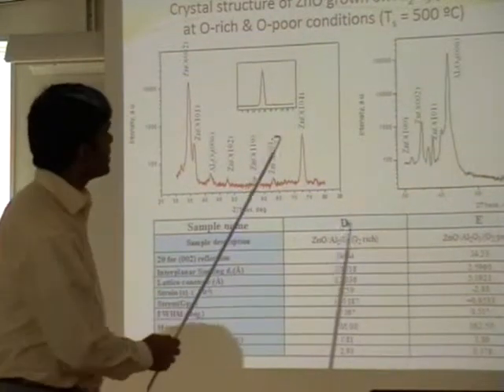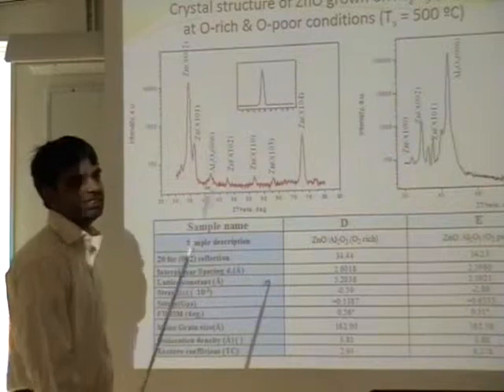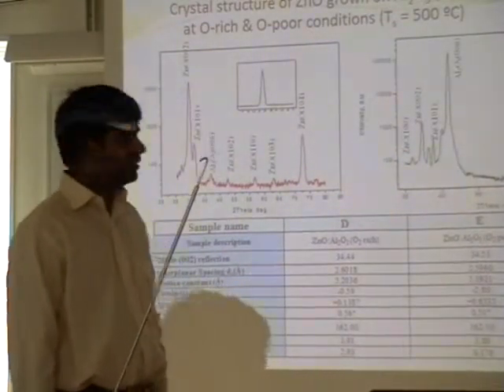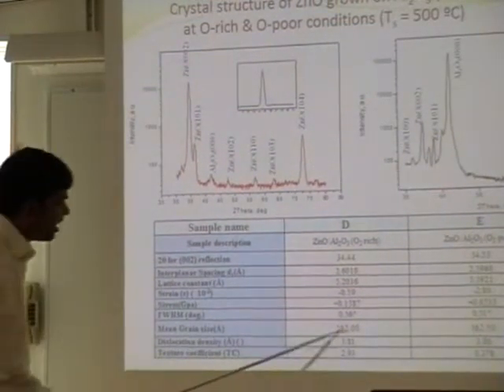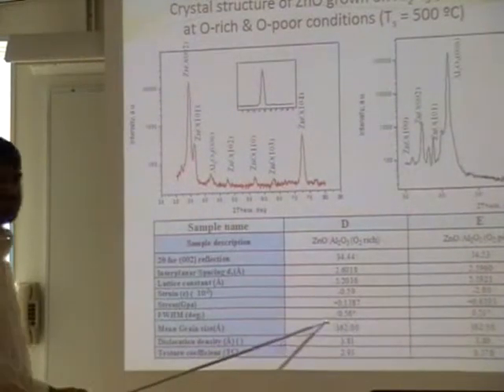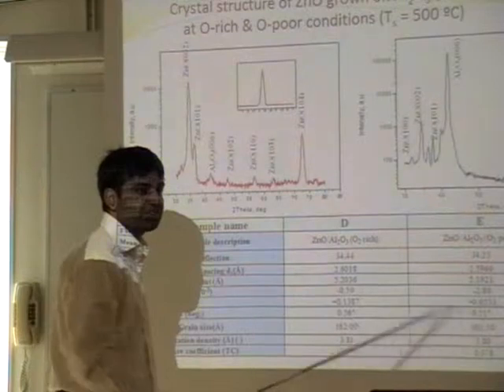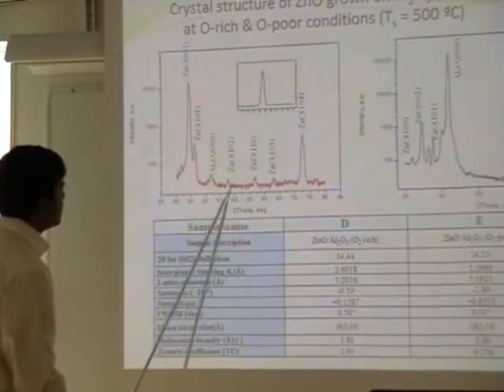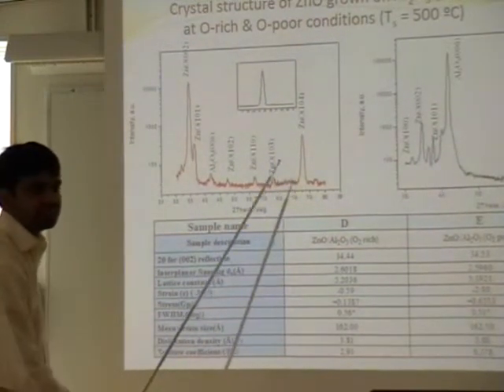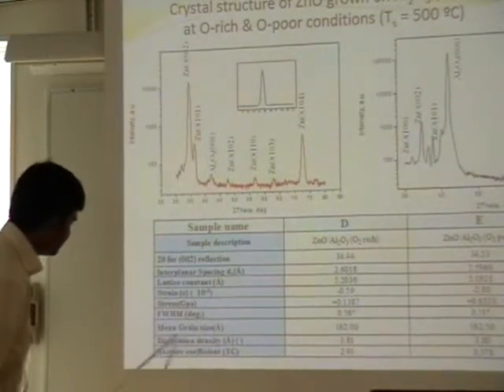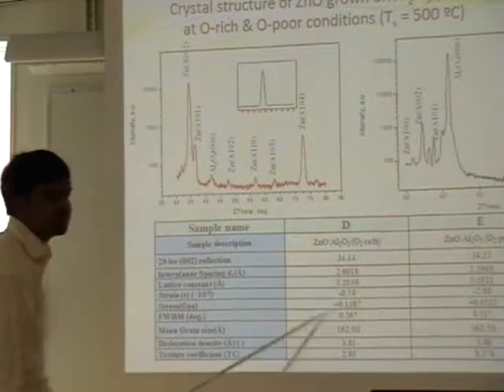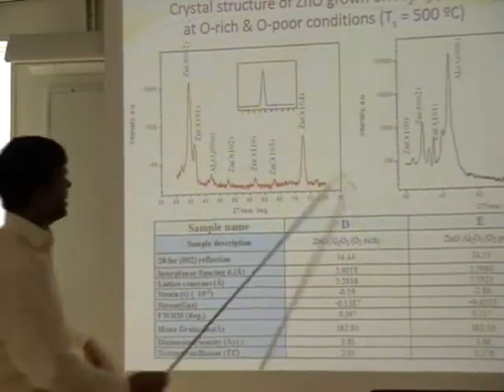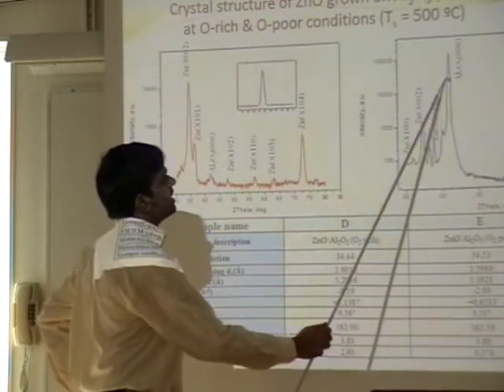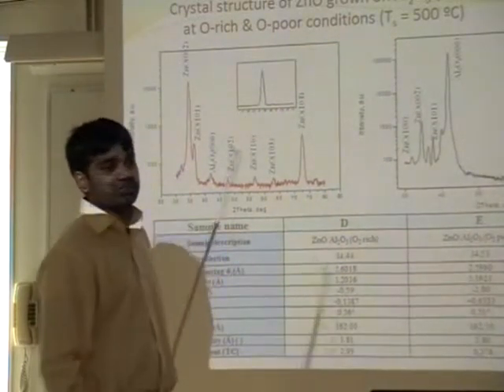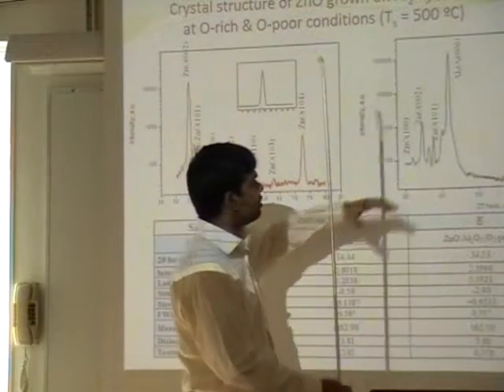The third section, the sample was grown by keeping oxygen rich or oxygen poor. Here you can see grain size almost the same, not so much effect. The full width half maxima is approximately the same, only difference. You can see these samples show a polycrystalline nature, having a large peak. Here you can see also texture coefficient is greater due to the polycrystalline film. Here almost all peaks are the same, except having a large peak from the substrate. Maybe the film is so thin, not so much polycrystalline, they possess the short peak from the substrate.